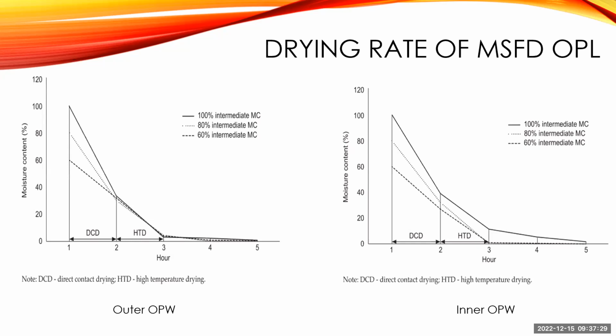So this is the drying rate of the modified super fast drying of oil palm method. The super fast drying is a combination, and we can see that it requires around 3 to 5 hours to reduce the moisture content of the oil palm lumber to less than 10%.